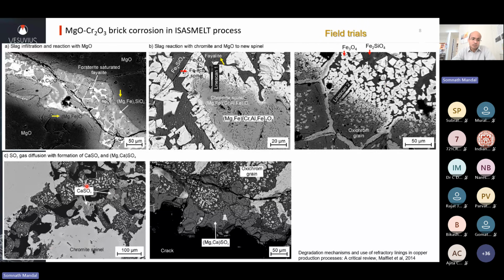Now you see in this bottom portion the gas phase reaction, corrosion. So you see calcium sulfate. This is the SO2 gas reacting with the calcium impurity present in the refractory, especially in the silicate phase, the monticellite phases, and it converts it to calcium sulfate. This is a porous, high volume product, and the refractory slowly breaks out from those regions. Here you see it more clearly. Oxychrome is a magnesia-chrome pre-synthesized aggregate, and you see this sulfate formation eventually forms a crack, and this high sulfate region comes out of the refractory and spalls off.